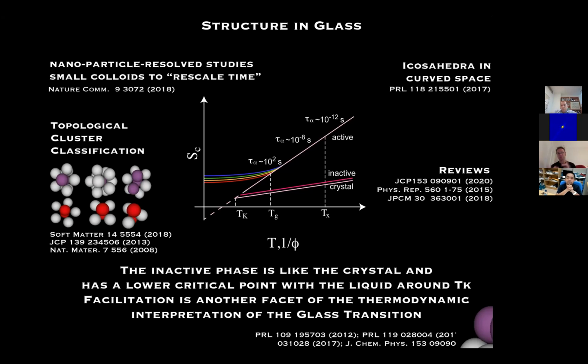We wanted to take a Gaussian core model, because the Gaussian core model in 3D has some mean field or high dimensional like behavior. And I expected that we could see something like what you say. I expected the local structure would go away, but actually it crystallized, and the simulations just didn't do what we wanted them to do. So the answer at the moment is that we have looked at the very polydispersed hard spheres, and there are local structures for them. They're sort of really deformed icosahedra in that system. So there is still a structure in it.